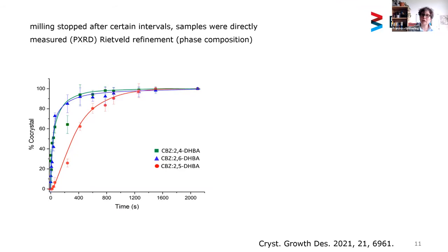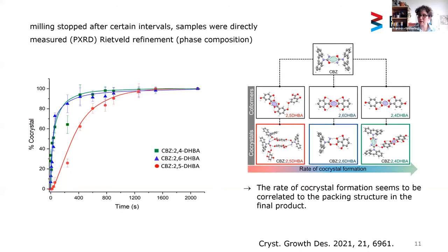And we tried to find a reason for that. And here we hypothesized that the rate of co-crystal formation is correlated with the packing structure in the final product. As I said, here in the case of the 2-4 compound, we preserve the homosynthon of the reactants. And here in the 2-6 compound, we have the strong new heterosynthon. And these two are much faster as compared to the other structure with the not so strong synthons formed.